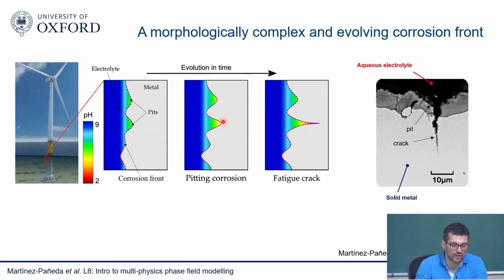As you know, of course, you are very familiar with mechanics. The sharper my pit is, the higher the stresses I will have ahead of my pit. The higher the stresses I will have, the faster the corrosion will happen. The sharper the pit is, also the more change in local electrochemical conditions I will see. So you'll go from a pH of 9, as you can see here, to 2. So there's a change of 80% in the pH and local electrochemical conditions from the bulk to the inside of the pit. So all of these things are very strongly coupled. The pit is growing due to mechanics, due to local chemistry, and the local chemistry and the local mechanics are themselves changing depending on the shape of your pit. So you cannot disconnect things. You have a problem that is strongly coupled, and you need to resolve everything that is happening there.